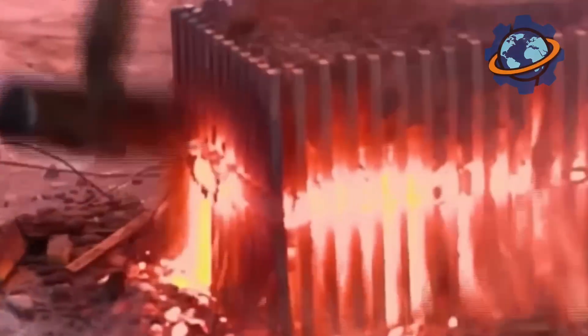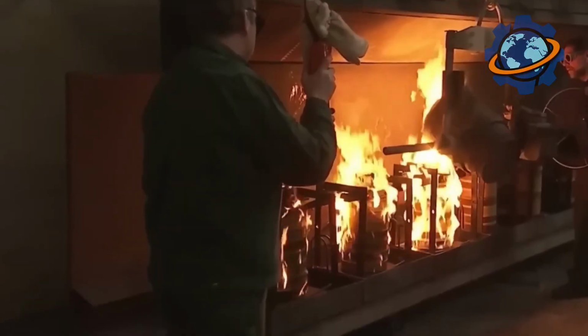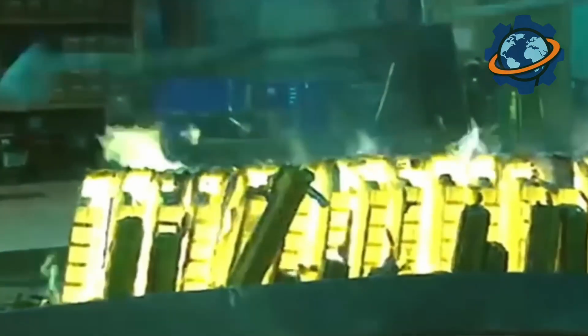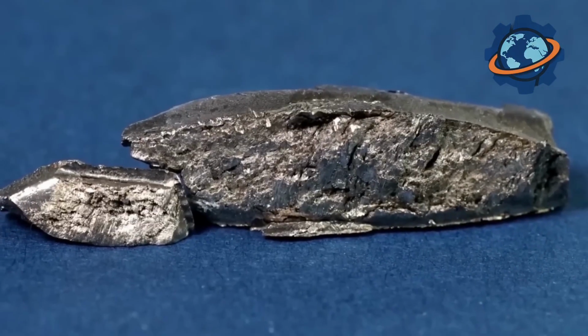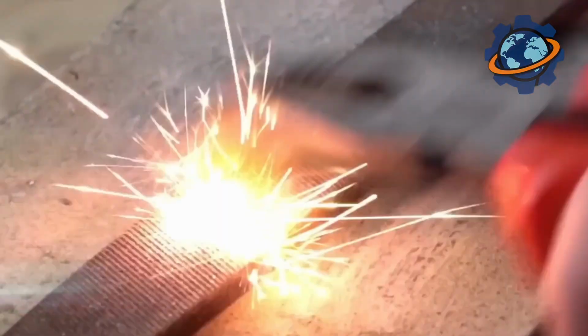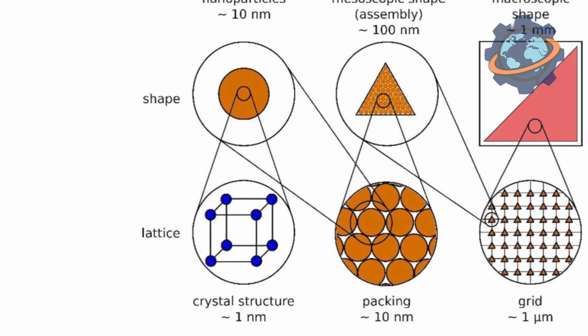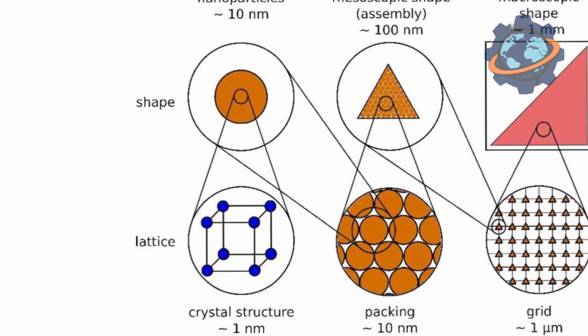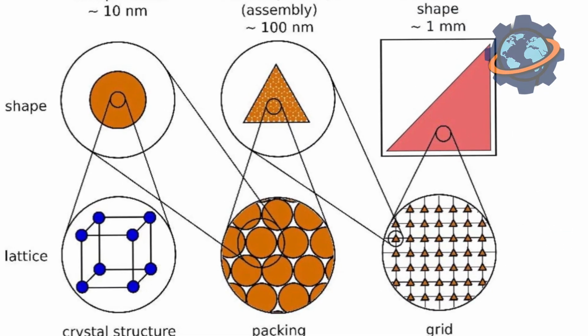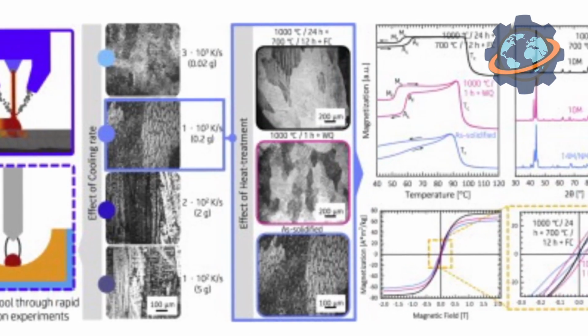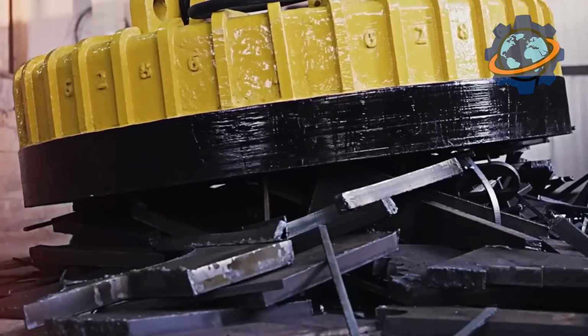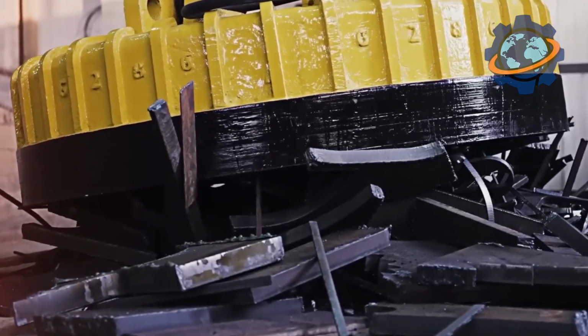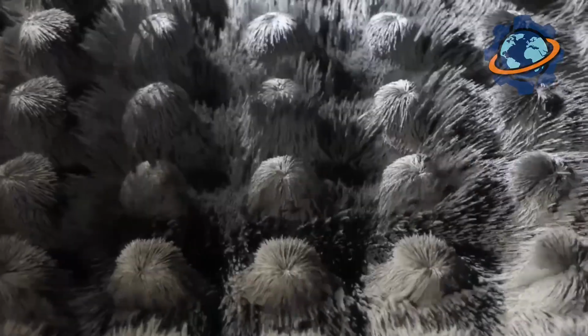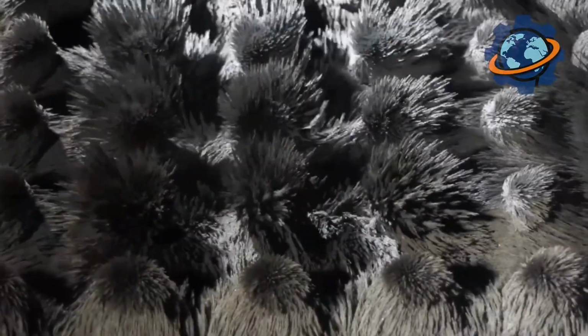This extremely rapid cooling prevents the formation of large crystal grains and allows for the formation of an amorphous or microcrystalline structure. Instead of the typical crystalline structures formed during slow cooling, extremely fine grains are formed. This process is also known as rapid solidification, and it is fundamental to achieving high magnetic properties. The resulting material takes the form of thin, easily crumbled flakes or ribbons.